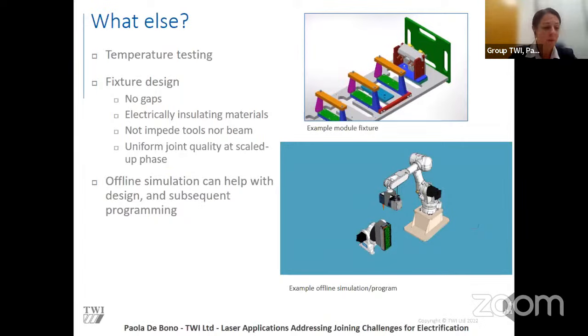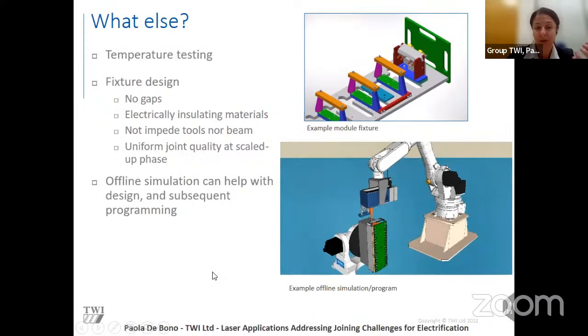So what else to consider for laser when joining for EV application? Definitely the temperature. There is chemistry within those battery cells. So typically it's important to control the heat input, avoiding going beyond the temperature threshold of those battery cells. The fixture design is very important, making sure there is uniform contact across the full battery modules, so validating those fixtures during the scale up phase. And in this context, also when developing parameters, let's say at coupon level, offline simulation has proved to be very helpful.